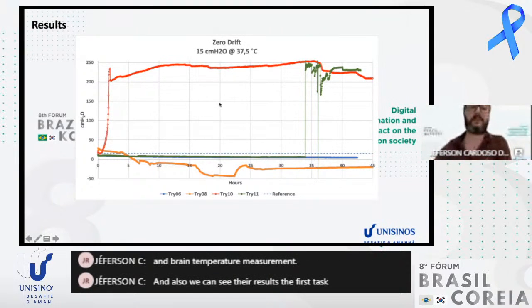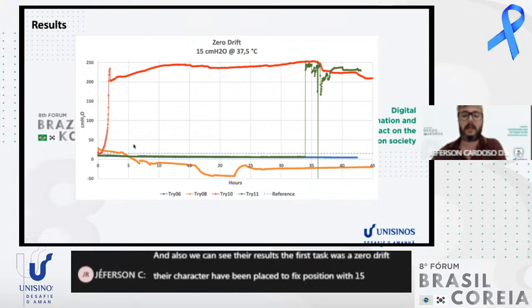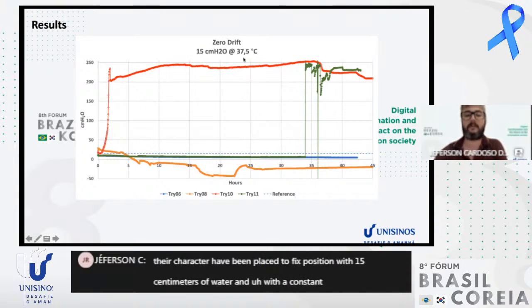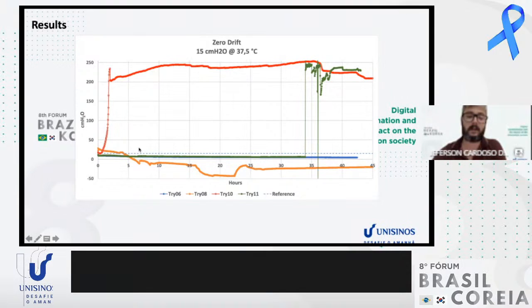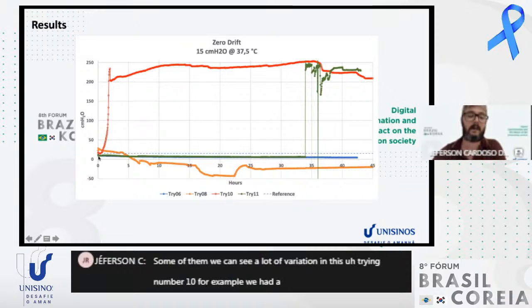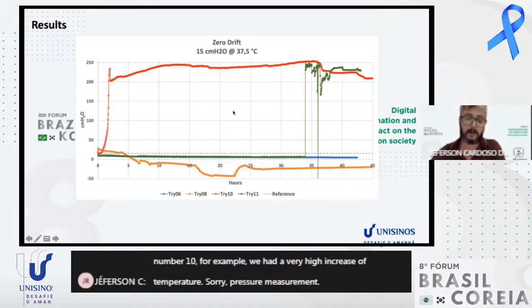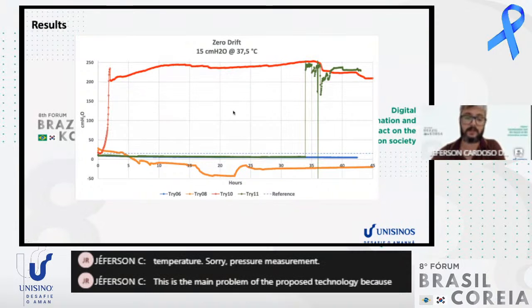The first test was the zero drift. The catheter was placed in a fixed position at 15 centimeters of water, with constant temperature, 37.5 degrees Celsius. The expected result in this test was this green line here. We can see the prototype number 11. We can see a constant pressure measurement along the time. In some of them, we can see a lot of variation, in this try number 10, for example. We had a very high increase of temperature and pressure measurement. This is the main problem of the proposed technology because we're using a plastic tip.